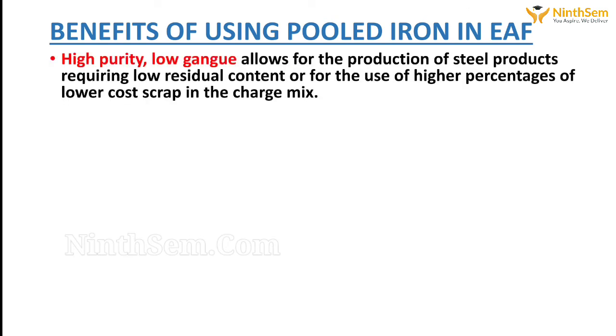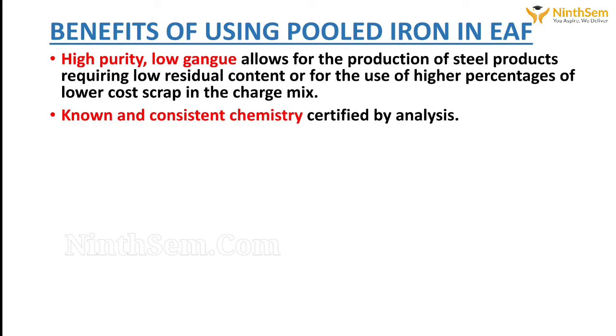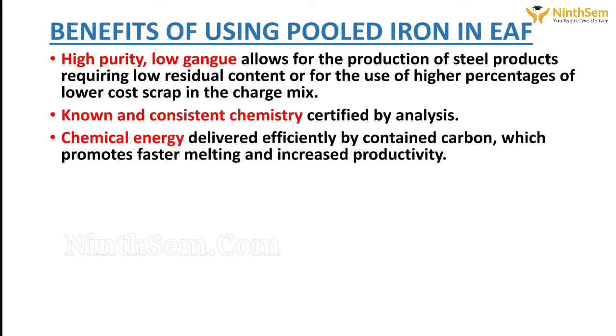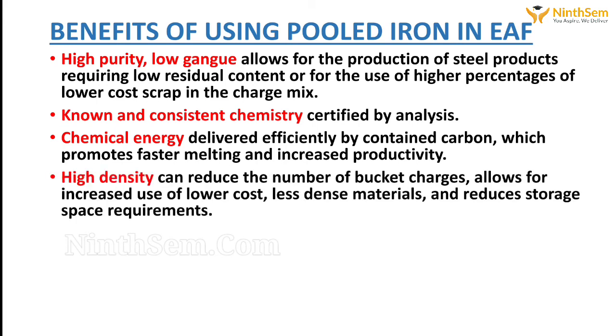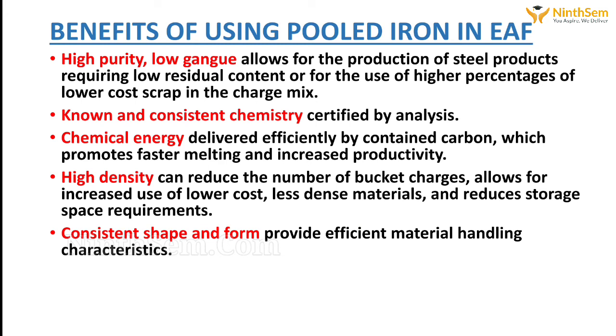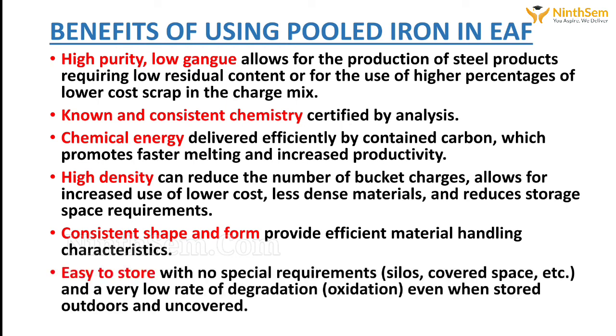What are the benefits of using pooled iron? High purity, low gangue, known and consistent chemistry, chemical energy delivered efficiently by contained carbon, which promotes faster melting and increased productivity. High density can reduce the number of bucket charges, allows for increased use of lower cost, less dense material, and reduces storage space requirements. It has consistent shape and form, and efficient material handling characteristics. Sometimes it is a chunk type shape. It is easy to store with no special requirements and a very low rate of degradation even when stored outdoors and uncovered.